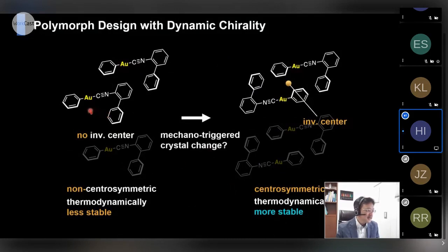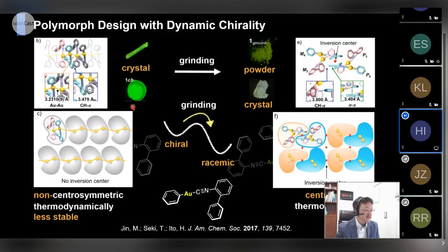If we can synthesize two crystals, one with non-centrosymmetric crystals, and the other with centrosymmetric crystals. And usually, non-centrosymmetric crystals, so-called chiral crystals, are thermodynamically less stable compared to the racemic crystal, which has a thermodynamically more stable structure. So we tried to synthesize chiral crystals, non-centrosymmetric crystals. We tried to grind these compounds. We succeeded in changing this structure to the racemic structure.